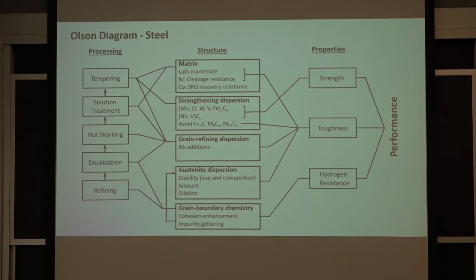You've said we're going to put this material in here because we know that during a post-quench tempering step, that material, if we can precipitate out these so-called M2C carbides, some metal plus carbon, we know that if we have this dispersion of these precipitates, the material will become tougher. So we just designed toughness in.